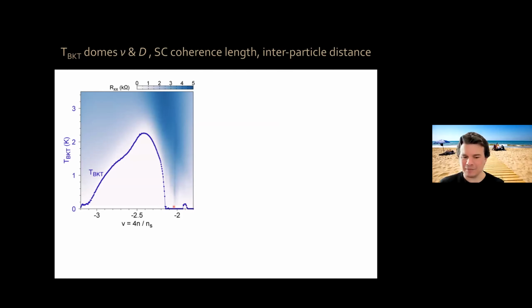So this is a TBKT as a function of filling factor at optimal displacement field. As you can see, we have this big dome for holes, a smaller dome for electrons. Along the same trace, I can also measure my superconducting coherence length, the Ginzburg-Landau superconducting coherence length, by doing magnetic field measurements. And this is what it looks like.